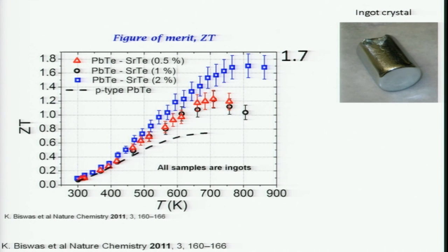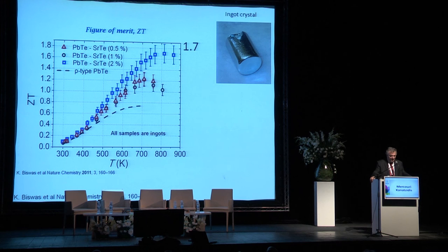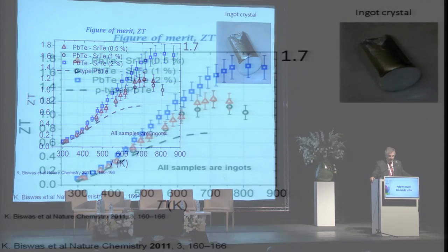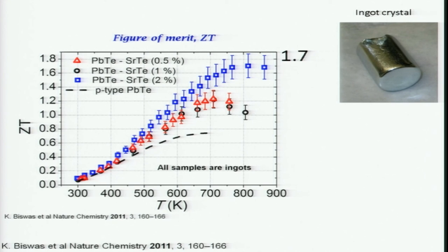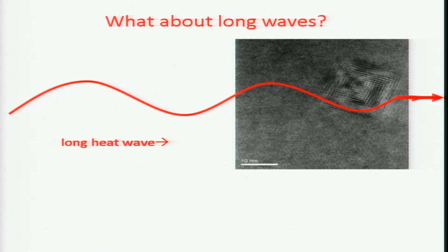With this recipe, you can actually make a breakthrough in ZT, which you see here in the blue data, that was coming up at 1.7, up from about 1.1, 1.2 of the previous generation material. This is the nanostructuring. And you see the sample in the upper right. But the thermal conductivity was still a little bit high, too high for us. We wanted to lower it even more.